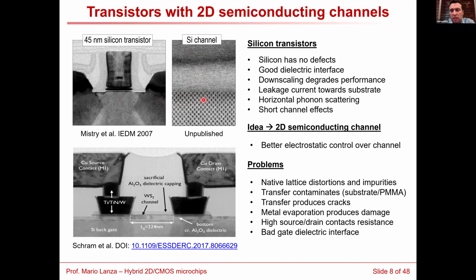However, when you make the device very small, you start to have leakage current towards the substrate, horizontal phonon scattering, and also short channel effects. The idea is that if we can make a transistor whose channel is atomically thin, we will have better electrostatic control over the whole channel, and therefore we may end up with better performance. Here you can see a cross-sectional TEM image of one prototype that has been fabricated by IMEC with a gate length of 224 nanometers. And this idea sounds very good. However, the problem is that,